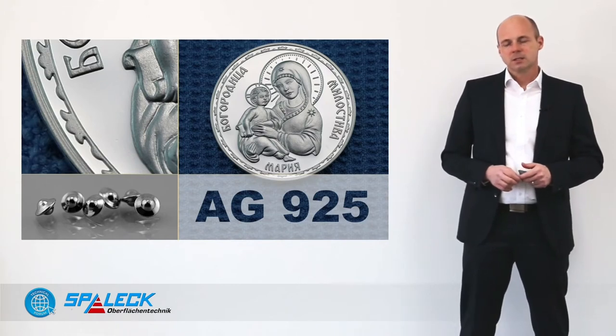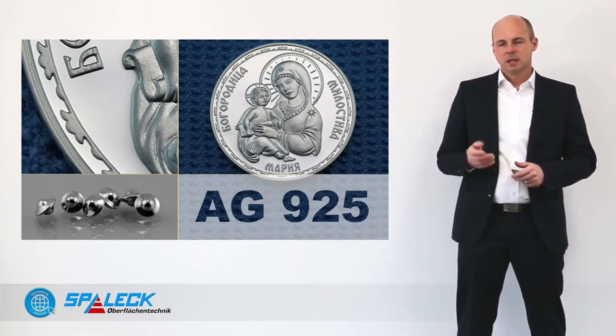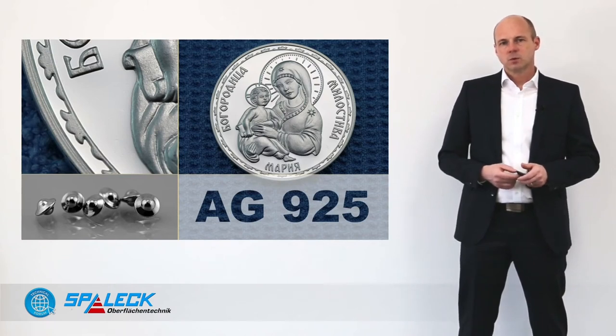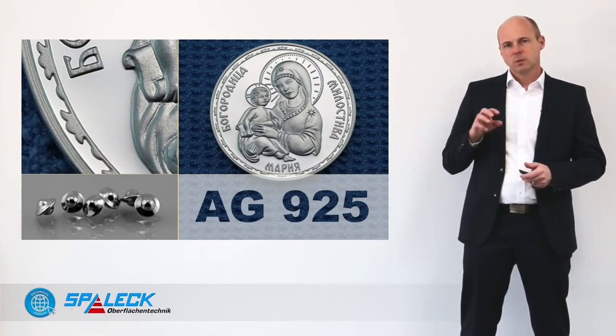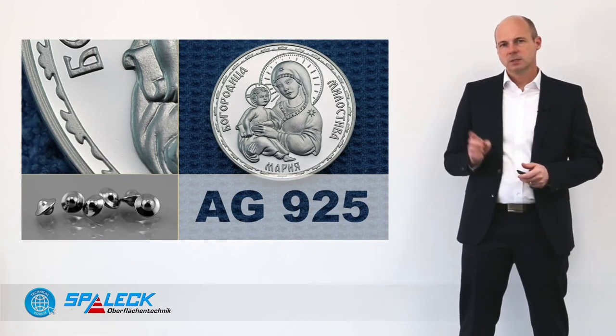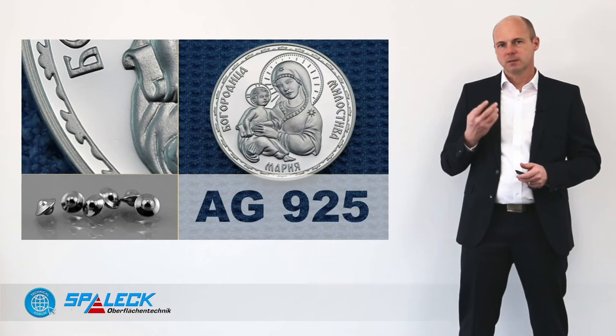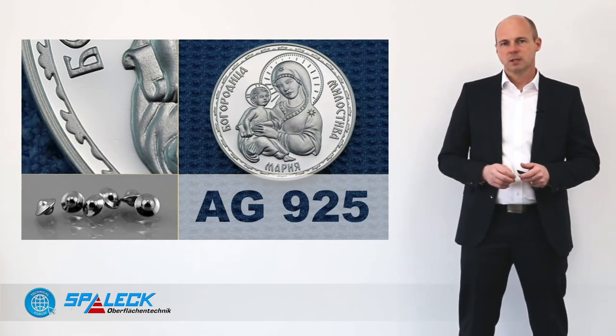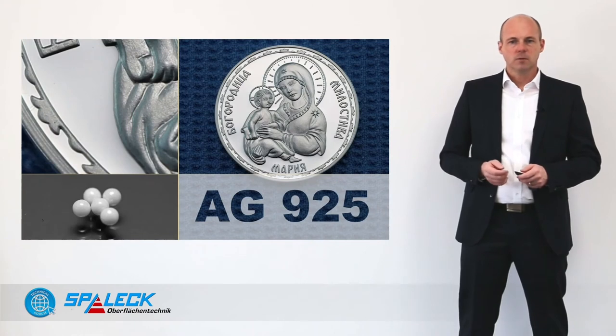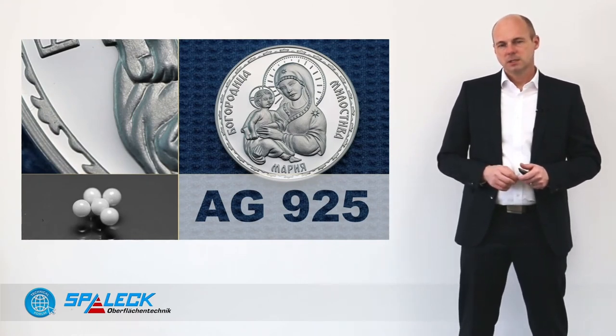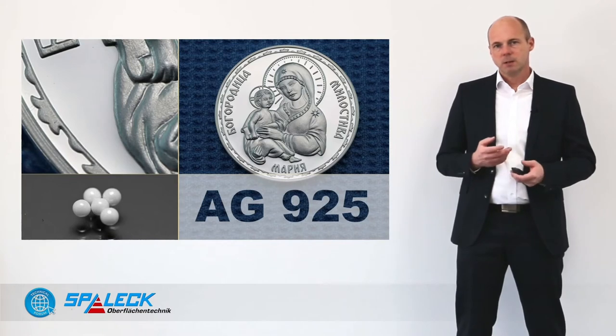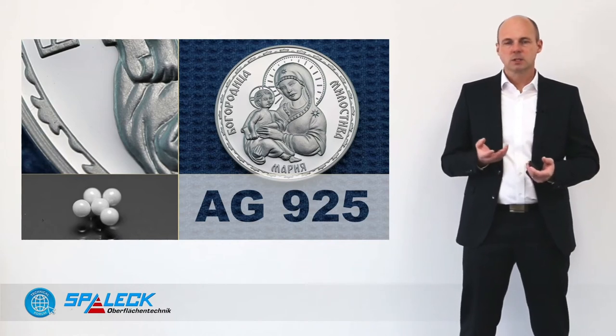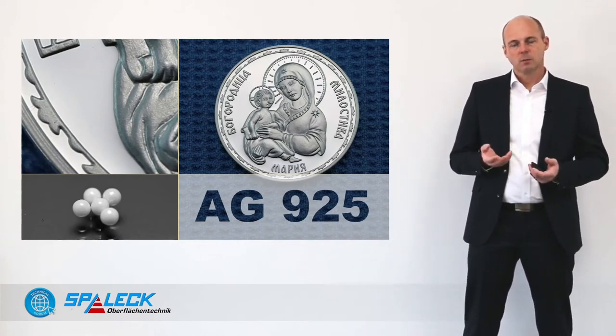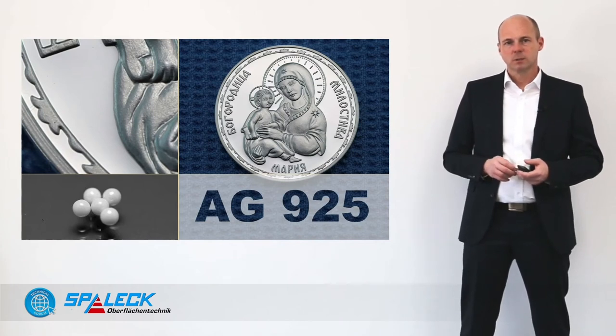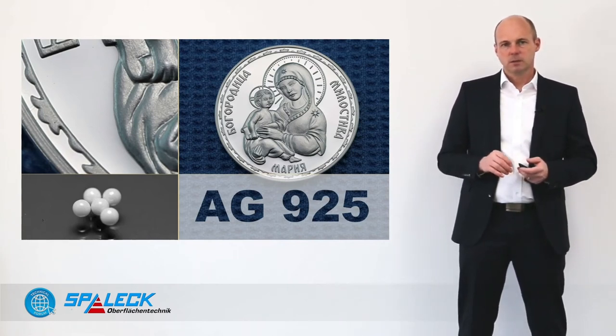First, we analyzed the sterling silver prepared by the satellites. Very good quality, proof level. But when you go really into the details, you see little dents created by that textured surface from the satellites. This can be avoided by using the CHD balls. Here we have the same clear, bright design and appearance of the coin with no defects, and on top, we also have no marks or visible textures in the table of the metal.